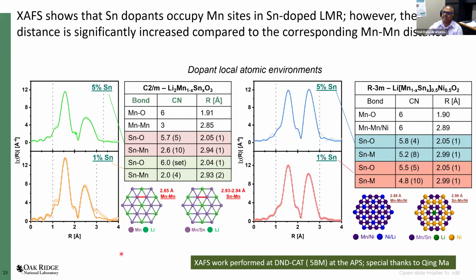We then followed this up with XAFS because we wanted to understand the site occupancy of tin. And we were able to show that the tin dopant occupies manganese sites in these materials. However, the tin-manganese distance is significantly increased compared to the corresponding manganese-manganese distance. In pure Li2MnO3, the manganese-manganese distance is around 2.85. In this case, the tin-manganese distance goes to about 2.93 or 2.94, so that's about a 0.1 angstrom increase in distance. Similarly, in these more complex materials, the bond distances increase from 2.89 to about 2.99. So this work, I should point out, was performed using Ching Ma's help at DND-CAT (5BM) at the APS